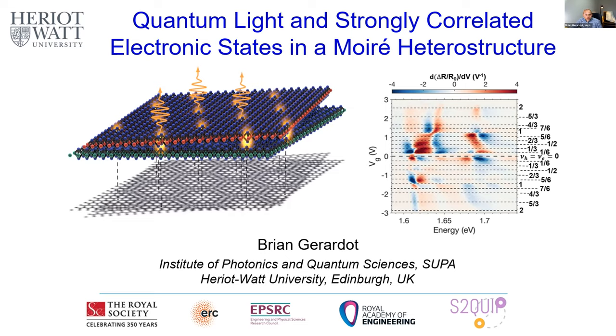So there are three contributions to the Zeeman shift band. We have the spin, the valley, and the atomic orbital. And these have various relations for the conduction and valence bands. And ultimately, it depends on the effective mass of the carriers in these cases. So like I said, I won't go into details, but if we measure g-factors, we can use these magneto-optics as a very clear signature of where the carriers are sitting in our structure in reciprocal space, by either probing the absorption or the emission.